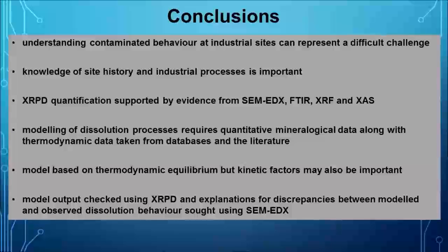We were able to carry out modelling. We identified that the dissolution processes were the important ones. You also have to be able to get the information in addition to your quantitative information. You need thermodynamic data. That's not always available from standard databases, and it may require scouring of the literature and some experimental work to get the necessary thermodynamic data. We were able to successfully carry out our modelling over a limited pH range using thermodynamic equilibria, but it was quite clear that there can be kinetic factors, and you can't overlook these when you're studying these complex systems.